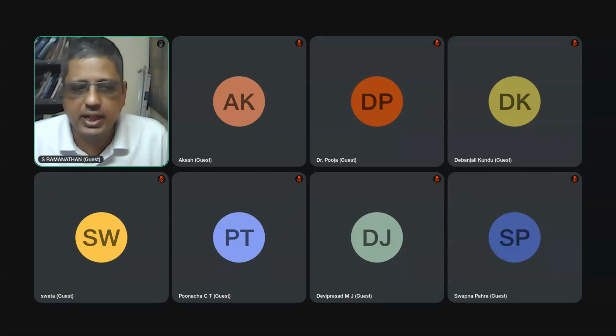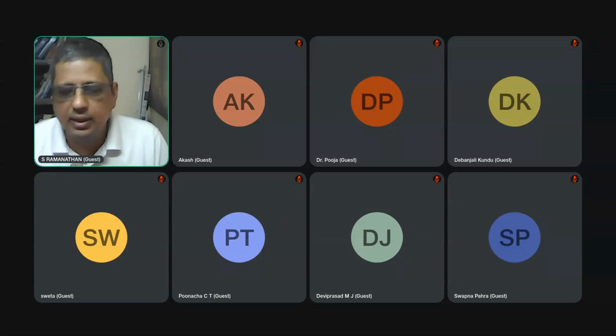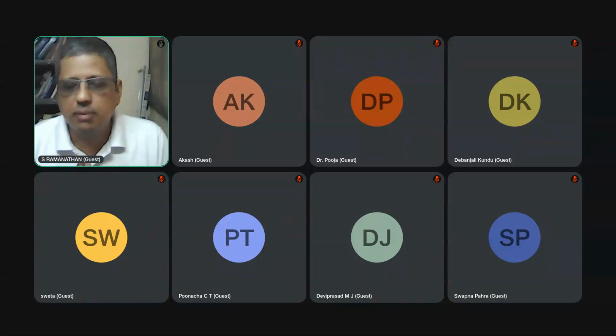If I give a large area, I need small current density for the same current. Let's say I have to push 1 amp within 1 second. If I use a small area, the current density will be 10 amps per centimeter square. If I use a large area, it will be 0.1 amps per centimeter square. The current density is related to the voltage. That means the potentiostat has to push the counter electrode only a little if you have a large area. So you're making the job of the potentiostat easier by giving a large area counter electrode.